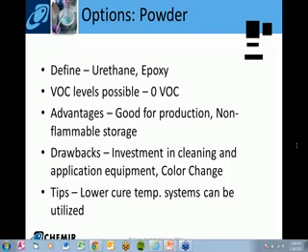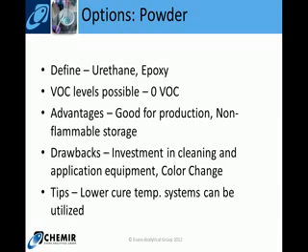Probably the first option for meeting any of these regulations is powder coatings. There are urethanes, epoxies, TGICs, and even hybrids. They are zero VOC or very near to it. The advantages: they're very good for large production runs, they store as non-flammables, parts are ready to ship after bake, you average a nice 2-mil film build, incoming freight costs are diminished because you're not shipping water and solvents, you need less room for storage, and these products give you a very durable finish. They've become widely accepted in many, many applications.